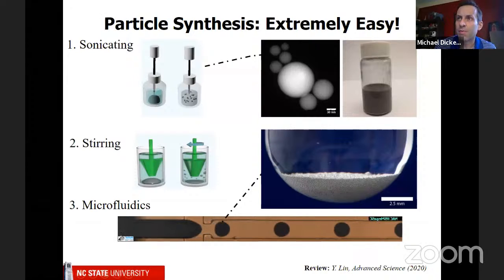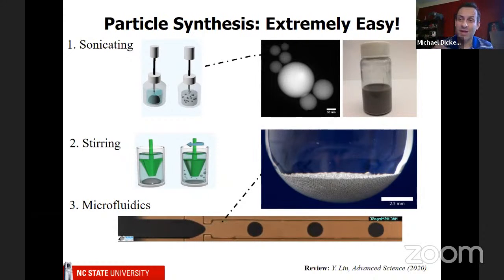And when we pump it, as it goes through this very small orifice, it causes the metal to break up into droplets. And this is actually taken with a high-speed camera, so it's actually going really, really fast. And we can make perfectly monodispersed liquid metal droplets, as shown in this picture.